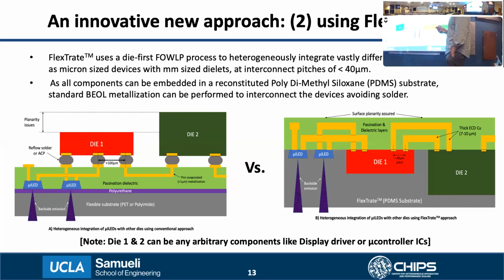But I think the point that Professor Bawakani is talking about is, if you had to heat sink this, the surface of the LEDs is available for heat sinking in this particular product, right? Yes. But as far as we know, there is no need to do that yet. Yes, you're right. Also, in the conventional approach, they usually use thin film metal or printed interconnects, which have a poorer thermal conductivity than in our case, where we use thick electroplated interconnects. So the interconnect layer here itself would act as a heat spreader to extract the heat from the LEDs and spread it out. But high power operation of these devices, especially very high brightness operation, would be an issue in both cases because the substrates have very poor thermal conductivity.